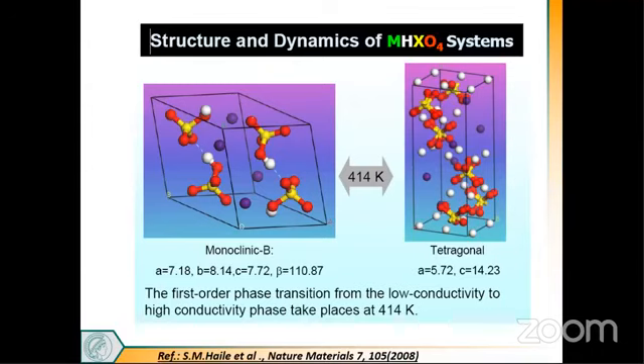There are many ways to check whether this mechanism is taking place at exactly this temperature or not. One of the methods, the simplest method, is to check via differential scanning calorimetry, which is available in the lab. So you can even see a kink at that particular temperature, which should be reversible. Here, this is the first order phase transformation from a low conducting to a high conducting phase that is taking place at 414 K. I will not explain first, second, third order Landau theory of phase transition, but I will just give you a glimpse.